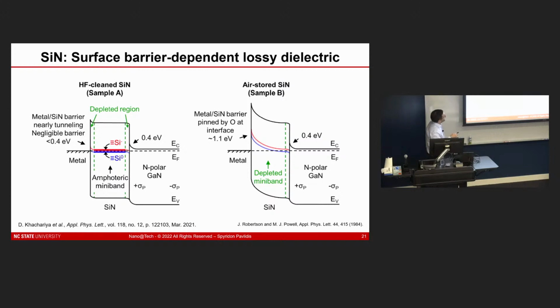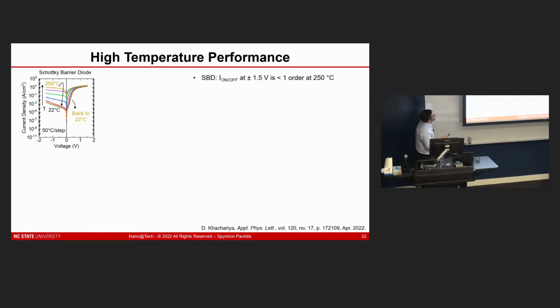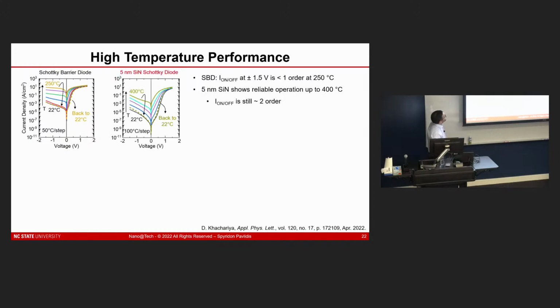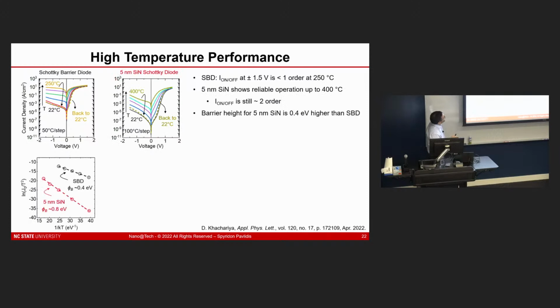And so you have to be very careful about how you treat these samples and how you fabricate them, and then ultimately that will have an impact on their performance as well. Now, not only did we tune the barrier to be larger through the inclusion of that interlayer, but we also demonstrate that we can now go to higher temperatures.